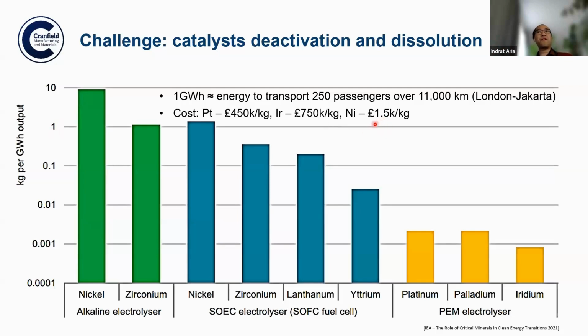Although nickel is very cheap, 1,500 pounds per kilogram, in accumulation, if we consume 10 kilograms of that, you can see it costs 15,000 pounds per flight just from the material consumption.